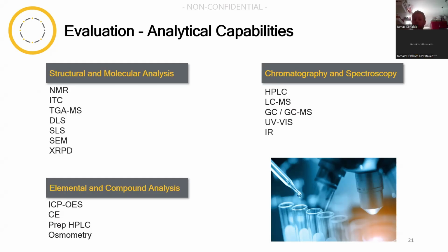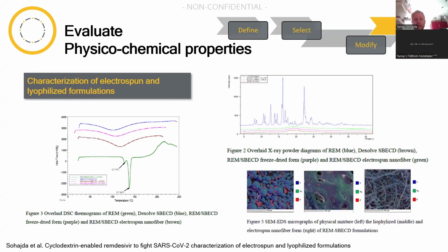So, just an example, the elution time on an HPLC of the naked active ingredient would be different than a complexed active ingredient. It will interact differently with the column. Same for most of the chromatography techniques. The chemical shift in the NMR will be different. The UV absorption will be different, and so on. So these are all potential tools to detect it.